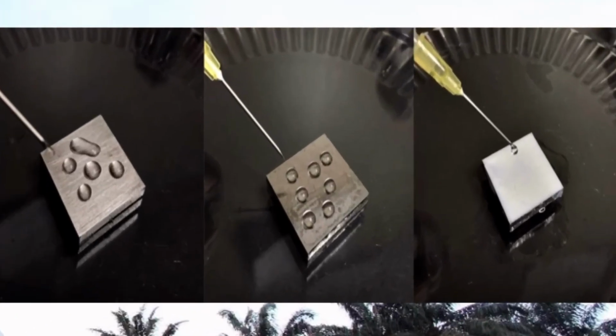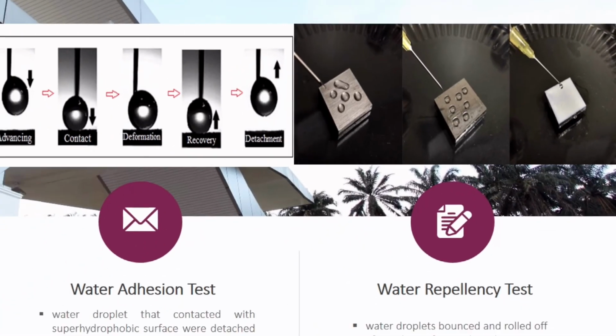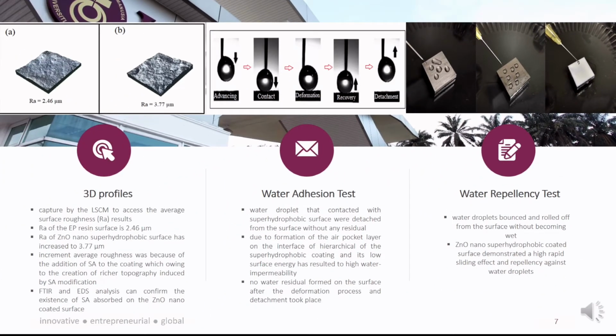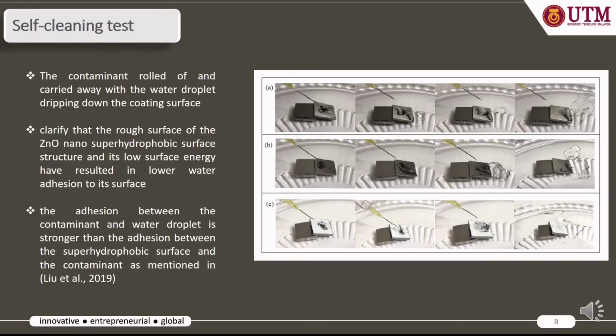This figure shows the water repellency performance of the blank metal and EP coating. However, on the zinc oxide nano superhydrophobic coating, water droplets bounce and roll off the surface without becoming wet. Based on the wetting characteristic and water repellency performance, the zinc oxide nano superhydrophobic coated surface demonstrates a high rapid sliding effect and repellency against water droplets, indicating its self-cleaning behavior. So next are the results of the self-cleaning test.